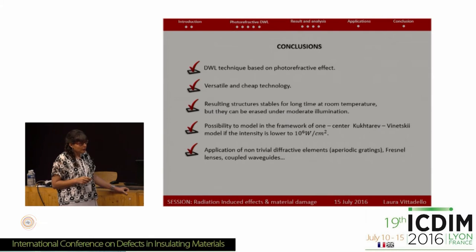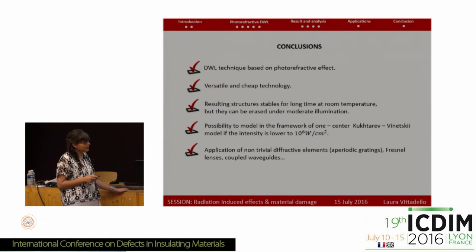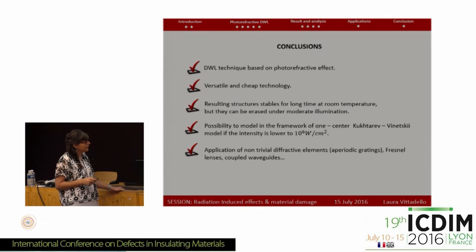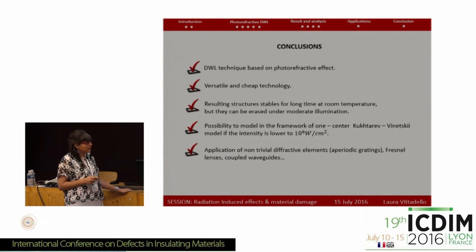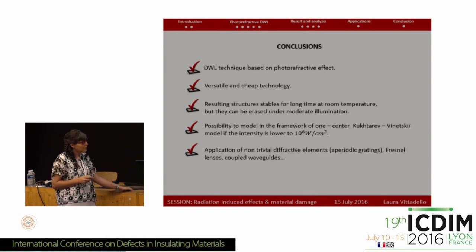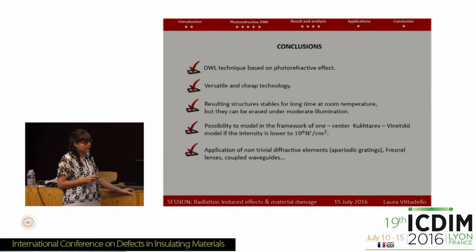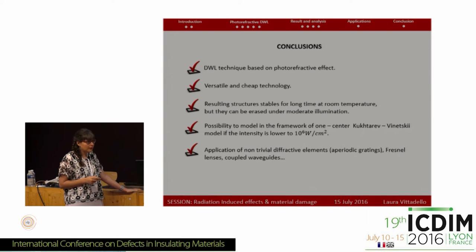In conclusion, I was able to create a new direct laser writing technique based solely on the photorefractive effect. This technique is more versatile and cheaper than the femtosecond laser technique. The results are stable structures that last for a long time but can be easily erased by heating the sample or illuminating it with an incoherent source. It's possible to model the results in an easier way using the one-center model, provided the intensity is lower than one megawatt per square centimeter. It's also possible to apply this technique to create non-trivial optical elements such as the diffractive elements shown, as well as optical waveguides that we have also tested.